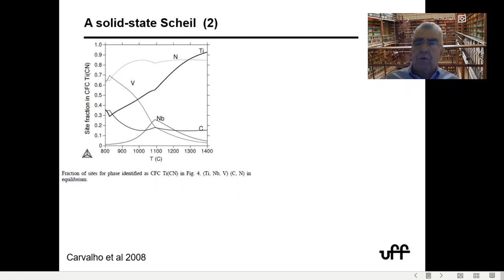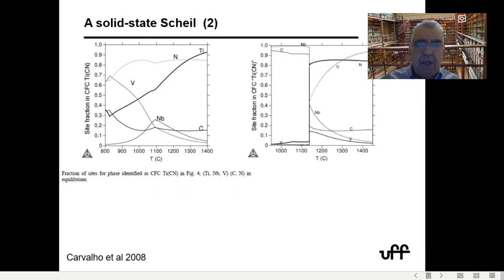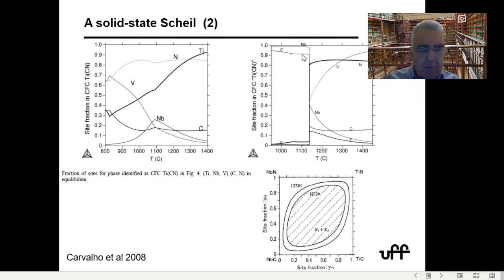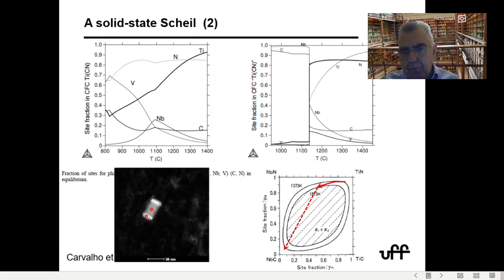If you recall the composition of the equilibrium carbonitride I showed you, now if we do the same with this SCHEIL model, we have a much different change. We have less titanium, so this is like forming in layers. We have that initial layer that is titanium nitride, and then it continues forming layers which are more and more rich in niobium until bang, you get to a point where it changes to niobium carbide. When you look at the phase diagram, there's a huge miscibility gap between the four compounds that it can form. This is happening because you're moving from the titanium nitride until you reach the miscibility gap, and then bing, you're coming this way. And this is what you see with these nice TEM pictures, where you have a core of titanium nitride and then these caps of niobium carbide.